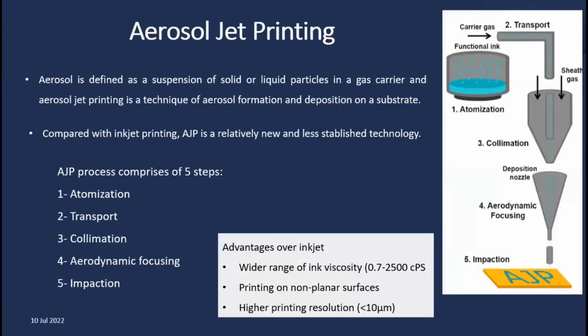Now, that was all about inkjet printing. So as I said, inkjet printing is great, but it has two major limitations. One, when it comes to electronic inks that you can print, you are only limited to a viscosity range. And the viscosity range is somewhere between, I would say, 10 to 50 cPs. Now, if you want to print materials which are outside this range, you basically have to find another way. The other problem is that most of the time when we are inkjet printing, we are only using flat surfaces, always 2D surfaces to print on. So if you have to print on a 3D surface, then you always have a problem.